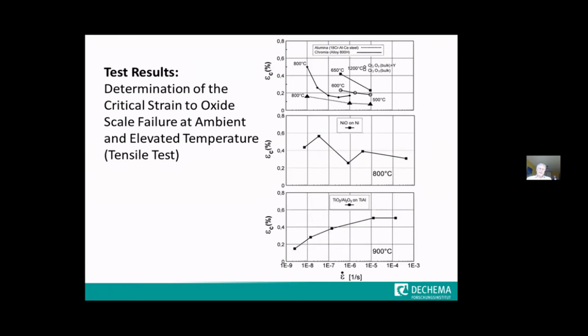It's quite low, which underlines the importance of the capability of such a scale for healing. If you would not have healing of such oxide scales, you would have a dramatic corrosive attack probably very soon in lifetime of these materials, since such low strains can always be reached under operation.